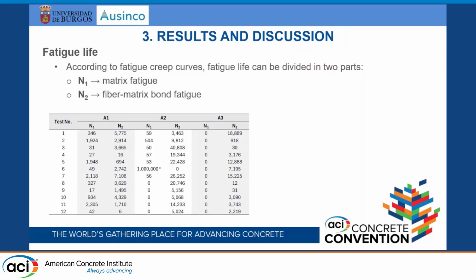With this reflection, with this proposal, we see that the number of cycles of a certain FRC specimen subjected to flexural fatigue can be divided in two parts: N1 regarding matrix fatigue and N2 regarding fiber-matrix bond fatigue. Here we have, for all the specimens, the differentiation between the two fatigue lives.